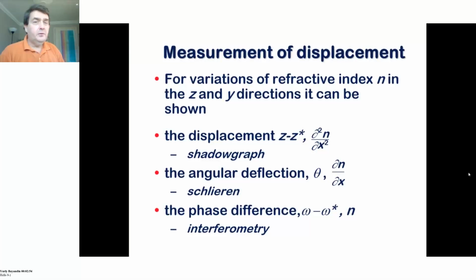And if you're doing different forms of interferometry or some forms of correlation, then the phase difference is the important thing you're after, and that's directly dependent upon the refractive index. So you have different techniques which record different levels of detail of the change in the material properties, of the change of the refractive index, and refractive index is very strongly dependent upon density.